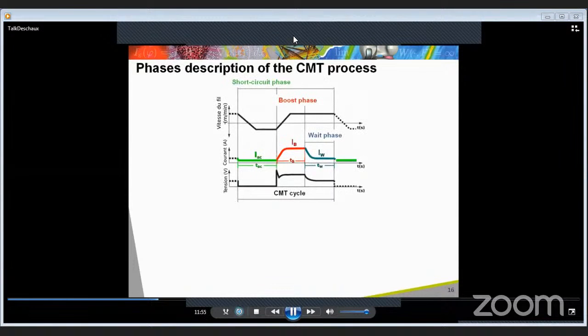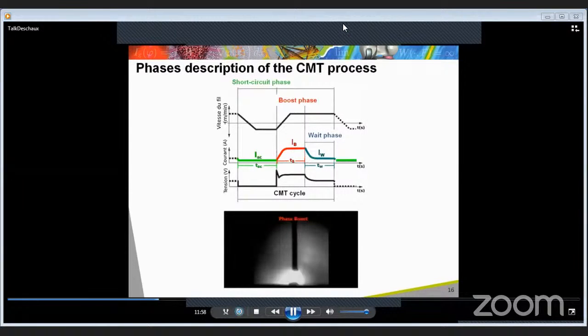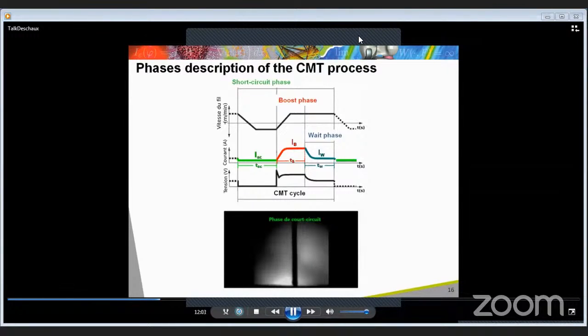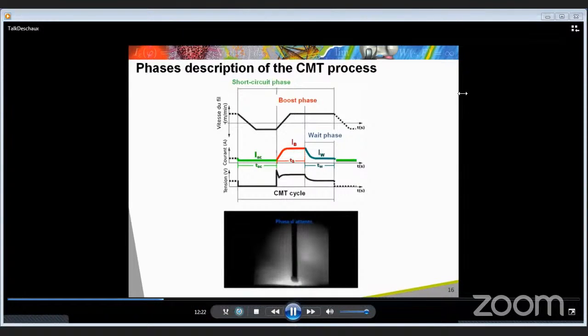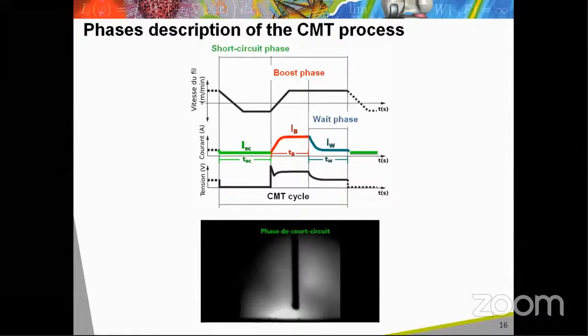During the transfer cycle, the electric current changes. During the beginning of the arc phase, a current pulse is created with a control current and a control duration. This phase is called the boost phase, in red in the figure. Then, the arc current decreases to avoid an excessive growth of the droplet and its detachment, and the wire is fed toward the workpiece. This phase is called the wait phase, in blue.